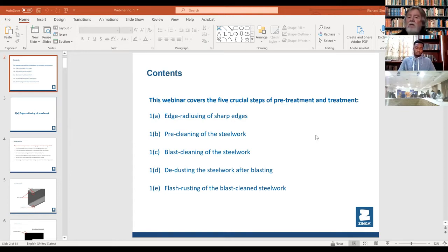The second one is pre-cleaning of the steelwork, because any steelwork, especially near the coast. I mean, when I was in Takoradi with Philip a few years ago, the humidity there was really, really high. So that means there's a lot of chlorides in the atmosphere. During the day, this salt is deposited onto the steelwork, and especially at night, when you have the winds blowing from the sea onto the land, it carries a lot of salt onto the steel inland, right up to about 10 kilometers. So pre-cleaning is normally at 150 bars to knock off all the salt that you can. And then after that, the blasting should remove the rest.